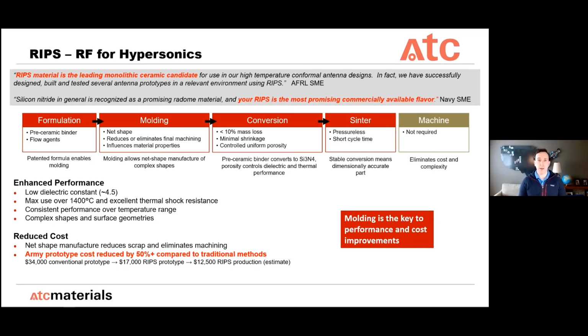Sintering is pretty conventional. And then machining, depending on the part, there may be some final machining that's necessary, but generally speaking, surface finish and everything else is good enough for use right after sintering. So that eliminates a lot of complexity. And as an example, we did work on an Army prototype, where about 50% of the cost of the Army prototype conventionally was machining. So 50% of the cost was buying the billet and 50% was machining the billet. And we can just make the part. The molding is the key to the performance, but it also affords the manufacturability.